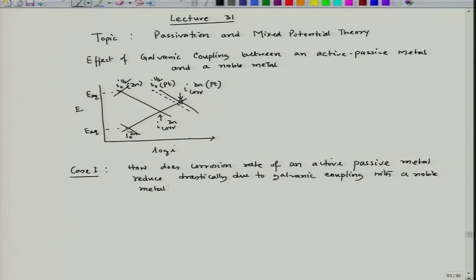So, this particular incident happens in case of titanium platinum alloy. Now, in this case titanium is an active passive metal, meaning its anodic portion first goes to an active region, reaches I critical, which is the maximum current density in its anodic polarization side, and then it reduces and reaches I passive, and then continues, and finally it has its own transpassive zone.